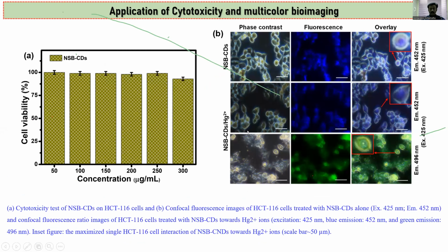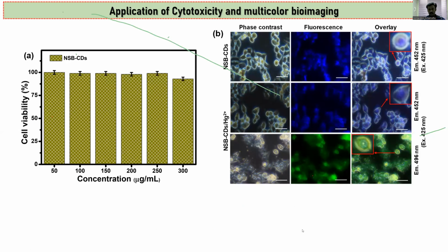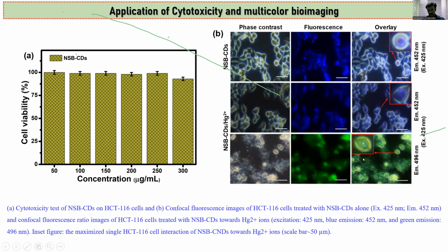For the biological application, first we have to measure the cell cytotoxicity, and we get a maximum of 90% cell viability. Then we apply the carbon dot with the carbon dot metal complexation. The first one is blue emission, and then we can get the phase contrast, fluorescence, and overlay images. We apply two different wavelengths, the first 452 nanometer as explained previously, and then 496 nanometer, so we can get two different color emissions. Here we can clearly see the intracellular carbon dot materials are more reactive with mercury ions. The scale bar used is 50 micrometer. We can clearly see that cellular tracking is very important for biological application in future.